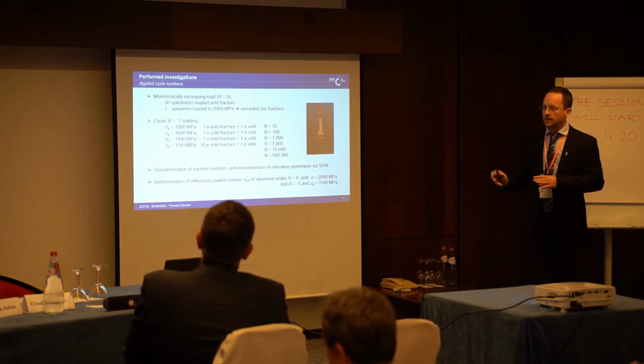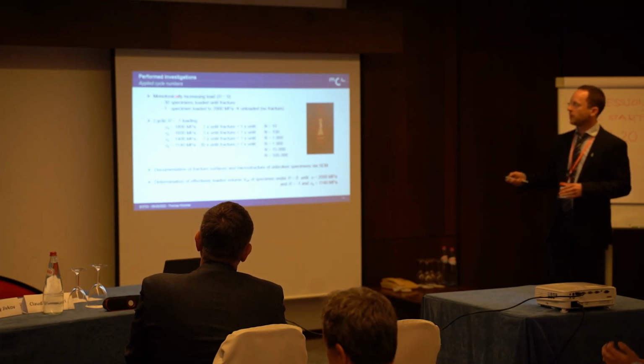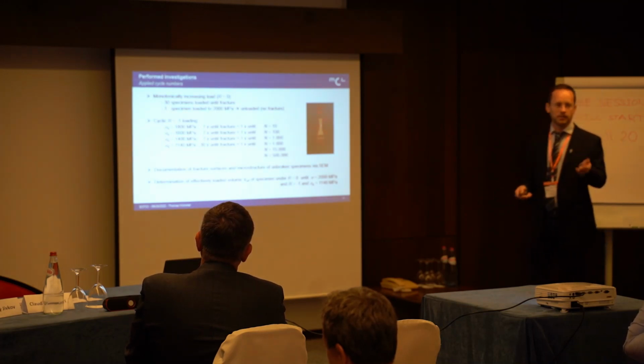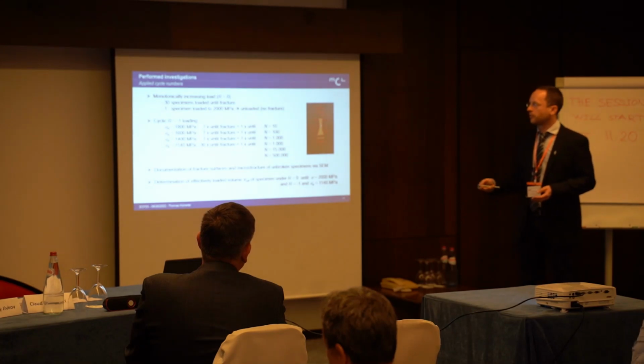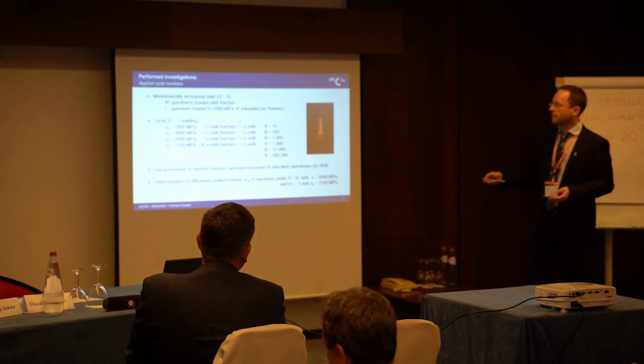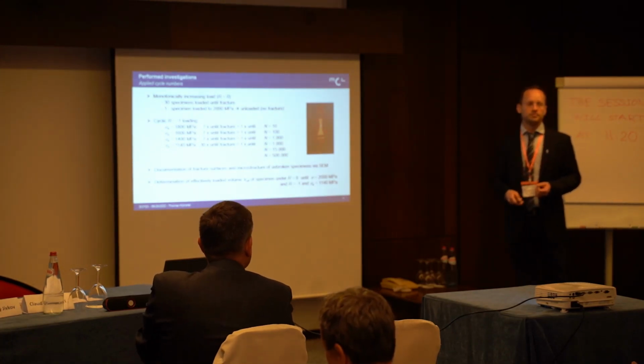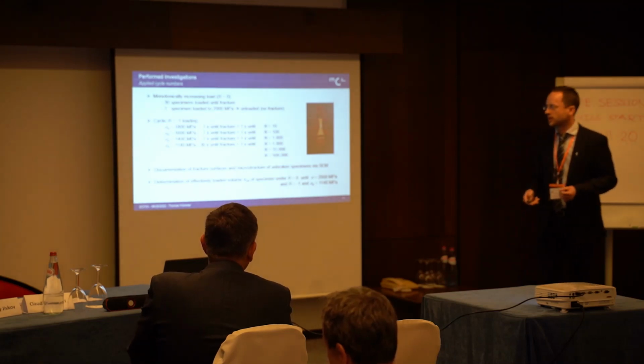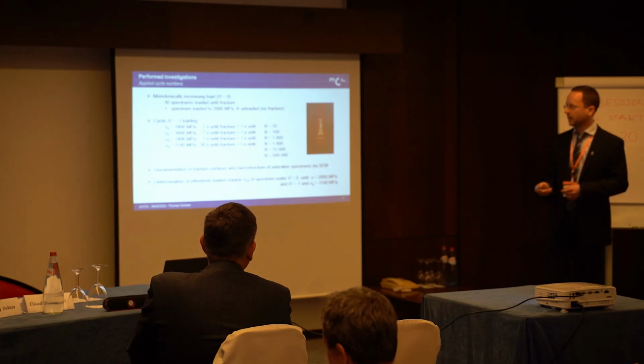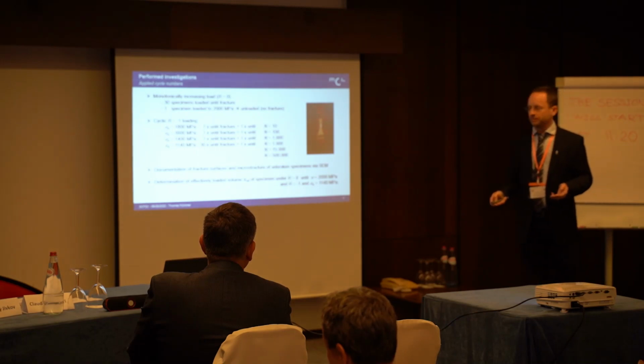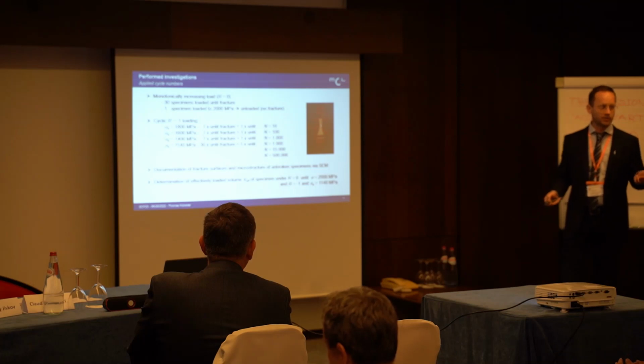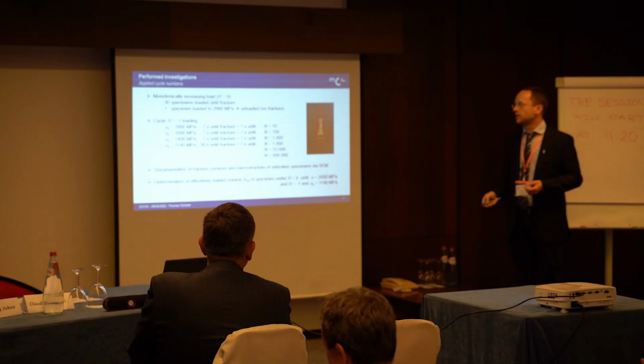Alright, so details I'll give in the paper. I just wanted to point out that, as the previous speaker pointed out, we did perform 30 experiments at certain stress amplitudes to have a statistical parameterization, so to say statistically meaningful information. We documented the fracture surface structure and the nature of origins of fracture, and we determined the effectively loaded volume of our specimens loaded onto the fracture at R0 and then R-1 close to the peak limit.